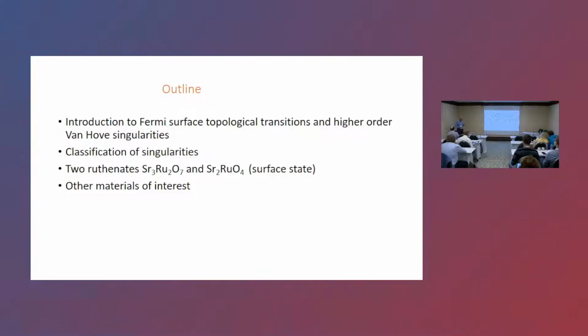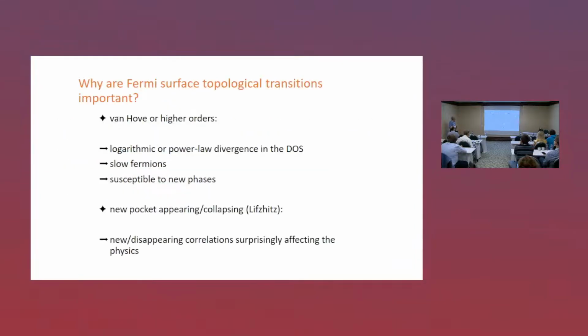And then I will move, because I was asked to present possibilities about van der Waals materials, so I will try to convince you that whatever I present in the first parts is of high relevance to van der Waals materials. So why are Fermi surface topological transitions and the associated Van Hove singularities important? In the case of the ordinary Van Hove, which I will explain mathematically if you like, we have a logarithmic divergence in the density of states in 2 dimensions. If you go to higher order Van Hove singularities, things become more dramatic because we have power law divergence in the density of states. Because of that, we have slow fermions, so the interaction effect becomes very important, and all these are susceptible to new phases.